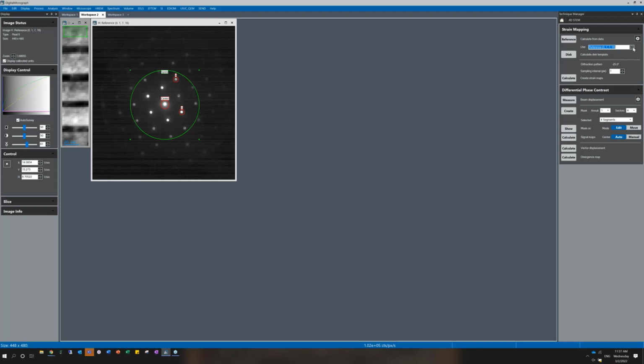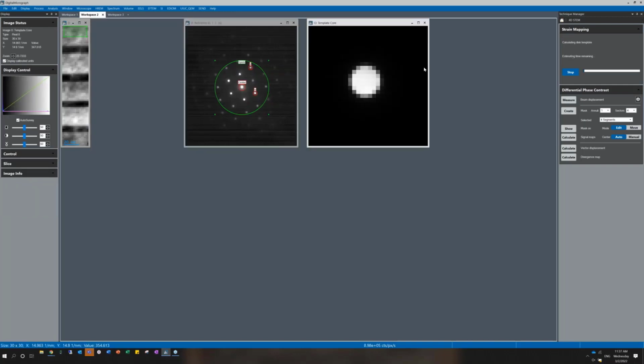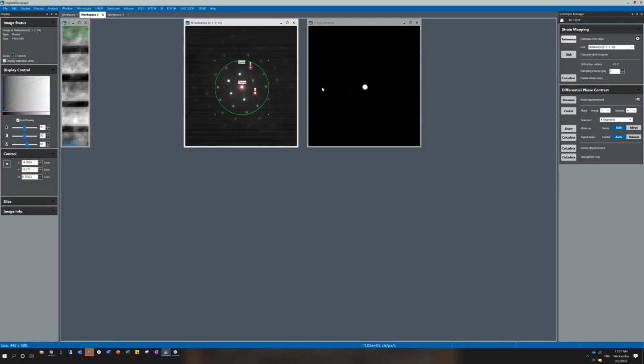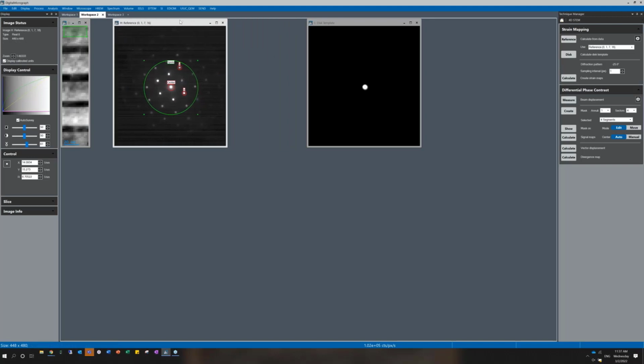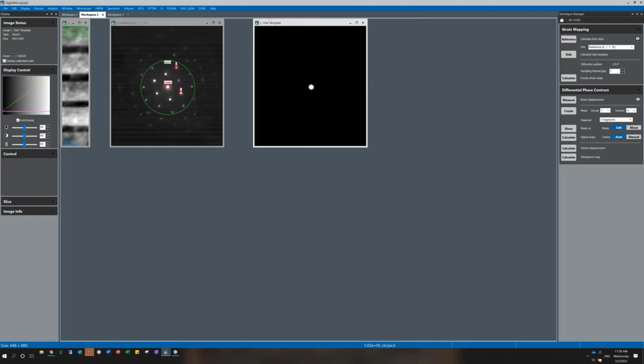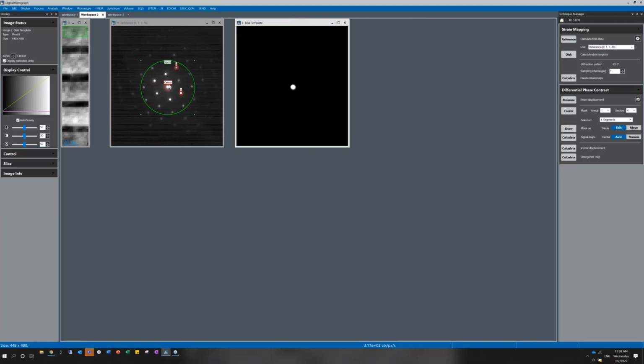You can have a standard sample that you don't expect to have any strain in. You collect a 4D STEM data set from that unstrained sample. You calculate the reference image from that data set, and then use that to measure the strain in your other data set. Okay, so once you have selected the reference diffraction image, we can calculate the disk template. I just click on disk, and it is now calculating the disk template using all the diffraction images in your 4D STEM data set from the central beam selected area that I have defined here by the red circle.